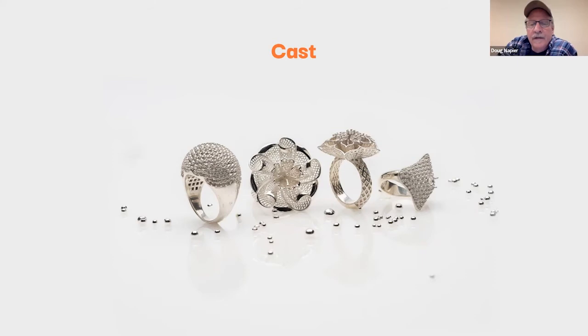It cast out well. And again, you've got to look at the piece and say, okay, how am I going to sprue this thing? So on the one on the far left, I had a sprue on the bottom and a couple of sprues on the shoulders. And then I had a couple of sprues on the inside of the shank, at the bottom of the ring itself, just so that it would feed a little bit better, because these pieces were really fine work. So you needed to control your feed pretty well.